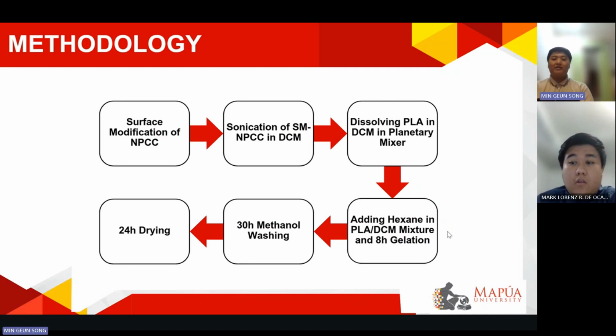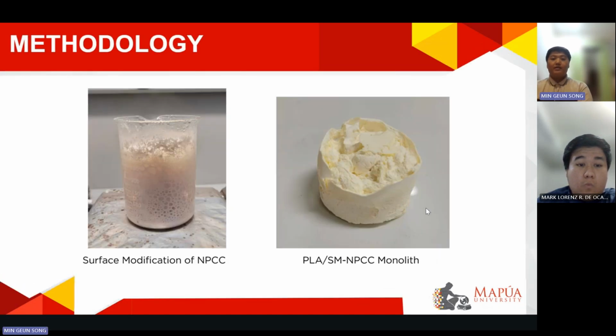Then, the samples were immediately washed with methanol under constant stirring for 30 hours and then dried for another 24 hours. Here is a picture of the surface modification process and a picture of one of the monoliths.